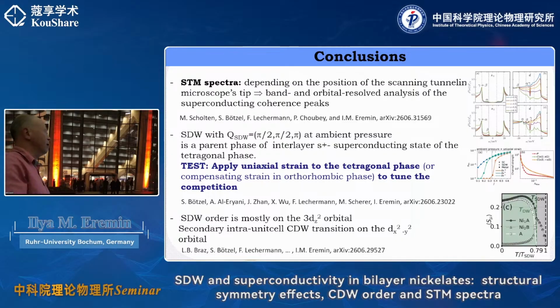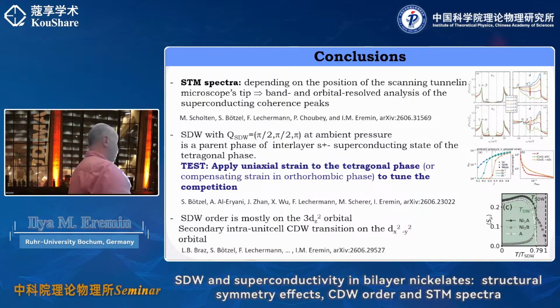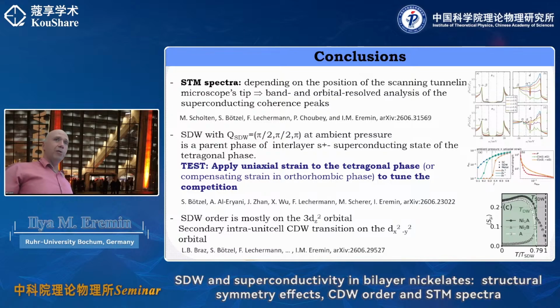An unambiguous proposal would be to apply uniaxial strain to tune the competition. And if you really look into the detail of the magnetic order within this itinerant Hartree-Fock mean field perspective, of course, again, you cannot predict the temperature of the transition. For that, the model is just Hartree-Fock, but you can still analyze the consequences of the magnetic order. You see that there is the charge order. It wants to develop also to form a spinless stripe order, and it would be further interesting to study this state. Okay, and this is also another reference. I have another part related to the stripes, but I decided that it would be too much. Okay, thank you very much.